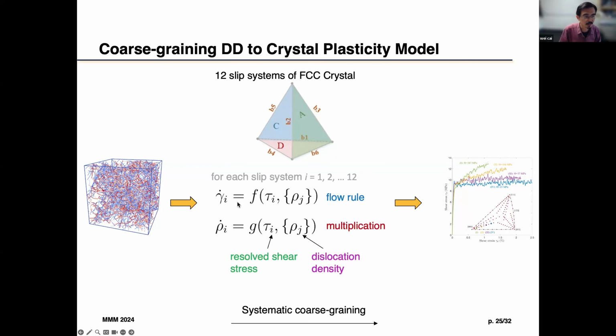In a crystal plasticity model, in FCC, we have 12 slip systems. So you basically say, okay, we want to know what is the shear rate on every slip system. So it's gamma dot i, i going from 1 to 12. And that usually depends on the resolved shear stress on that system, and also some microstructural parameter, which let's call it dislocation density. And then the dislocation density itself also evolves. That would depend on both the dislocation density on other slip systems and the resolved shear stress. So you can say it's pretty complicated, but this is a set of ODEs, right? That has only 24 degrees of freedom. So it's a great simplification from the full DD simulation.